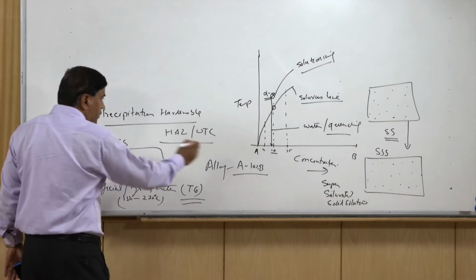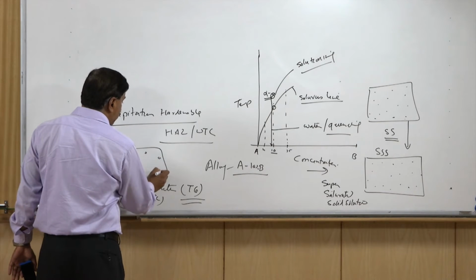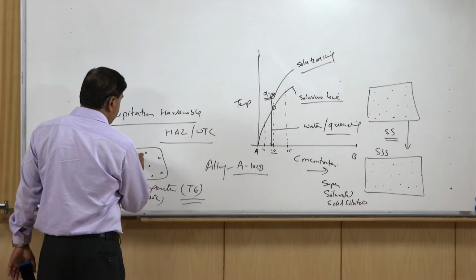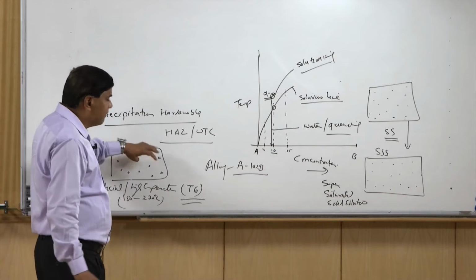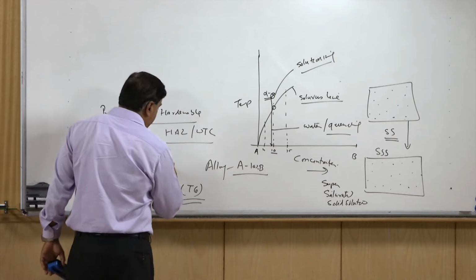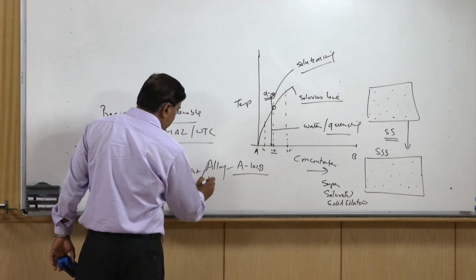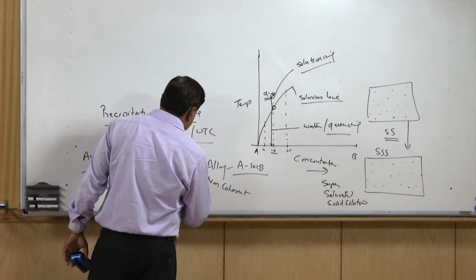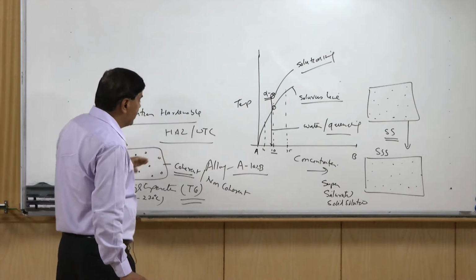So, during the high temperature exposure, the supersaturated solid solution starts forming precipitates uniformly in the matrix. These precipitates, depending upon the kind of alloy or alloying elements, will form different types of precipitates. These fine precipitates can be coherent or non-coherent. The coherent precipitates help to strengthen the alloy significantly as compared to the non-coherent precipitates. So, in this way there are 3 steps in precipitation hardening of the metal systems. One is solutionizing to form the homogeneous solid solution, second is quenching to form the supersaturated solid solution, and third is aging. Aging may be done at a high temperature for artificial aging, or it may be done at room temperature for natural aging.